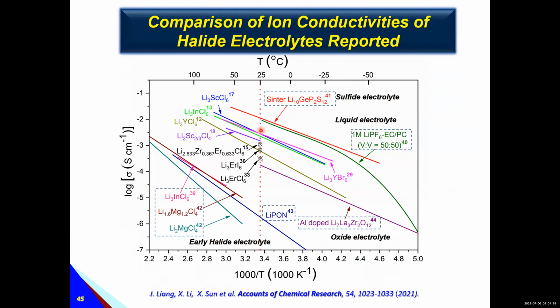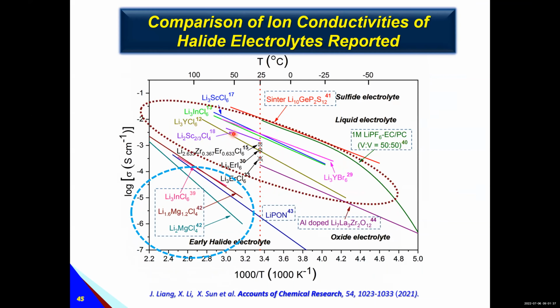We have a summary here talking about this halide-based electrolyte. In earlier years, very low ionic conductivity. In recent years, we can increase ionic conductivity, but there is still room. Compared to sulfide-based, we still have big room to work on. So how do we get higher ionic conductivity, increase it 10 times?